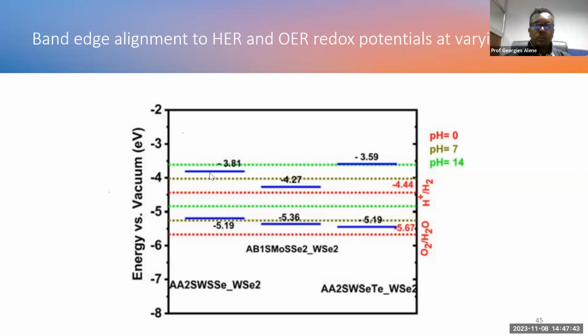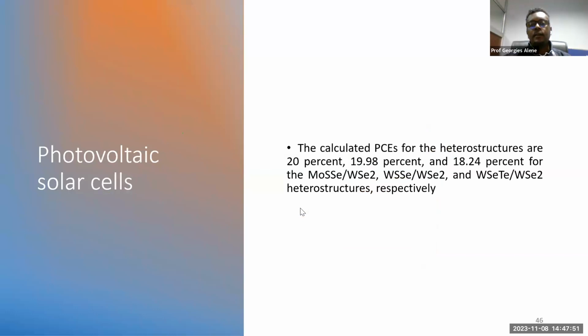And again, for different pH values for the different materials, we investigated and summarized the results. Finally, we have calculated the PCE value, the power conversion efficiency value, for the heterostructure. And we got like 20, 19, and 18%, which is good relative to other published results in the area. And we believe these heterostructure materials are good for photovoltaic application.